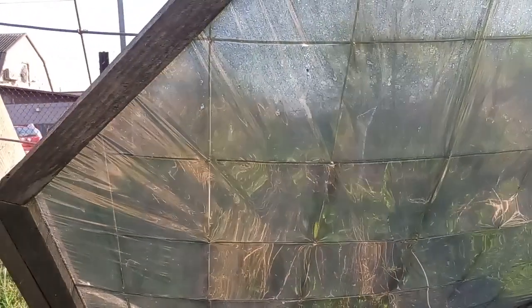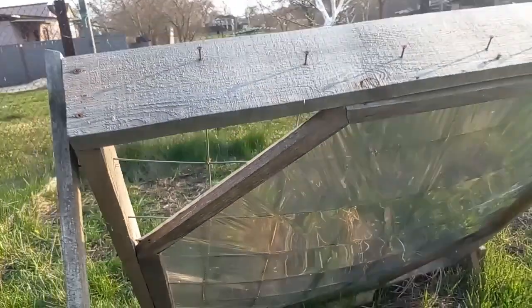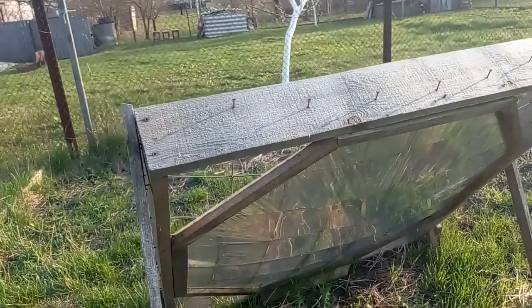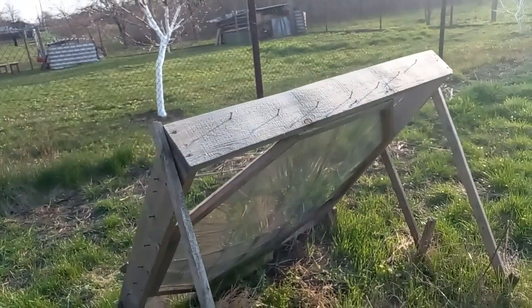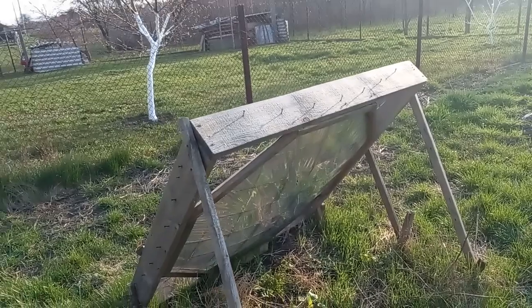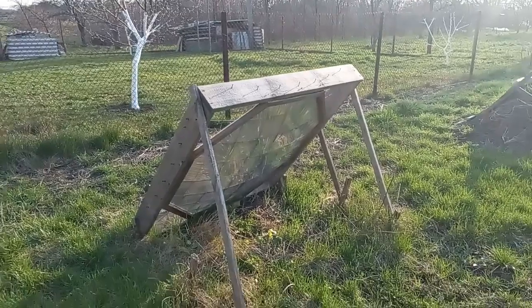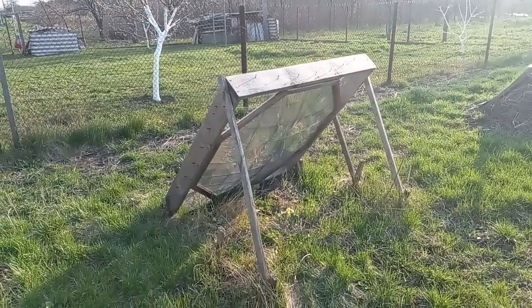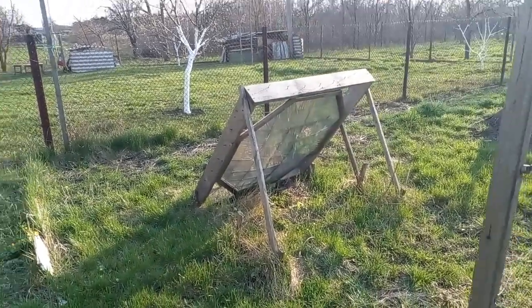This phenomenon not only reduces the reflectance of the mirror, but also accelerates the aging of the mylar layer due to solar radiation, because that aluminum layer is on the sunny side of the film — that is, on the south side — and therefore it protects the mylar from solar radiation. If the aluminum layer were on the opposite side of the film, that is, on the north side, the lifespan of the film would be only a few months because the solar radiation would quickly destroy the mylar layer.